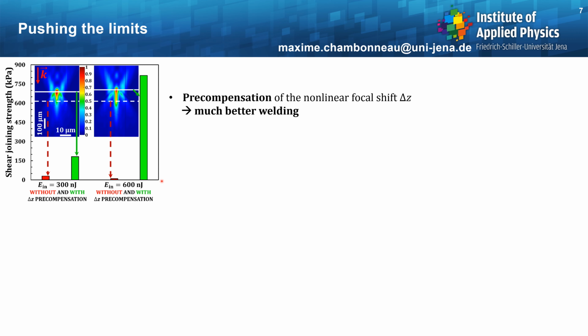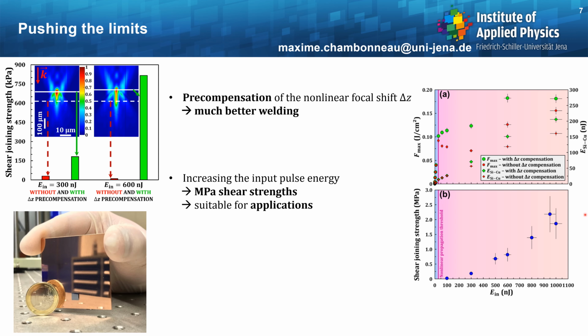Okay, so now what if we increase the input pulse energy and at the same time keep this precompensation strategy for the nonlinear focal shift? Well, the results are essentially shown here in terms of shear joining strength as a function of the input pulse energy, and one can see that it is possible for around 1 microjoule to reach a shear joining strength of around 2.2 megapascal, which is suitable for applications. And the reason for this success is that precompensating the nonlinear focal shift delta Z leads to an enhancement of the maximum fluence reaching the interface, and simultaneously it leads to an enhancement of the energy reaching this interface.